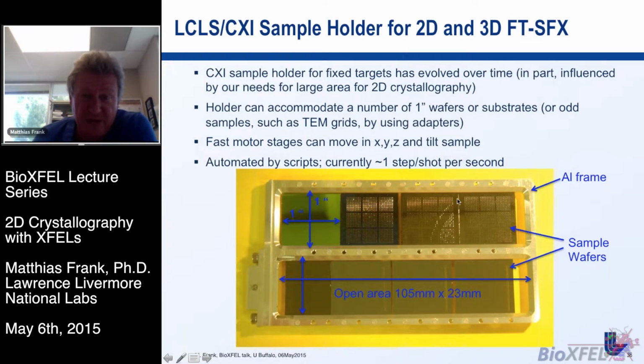So here's an example of one of these sample holders that we used at LCLS. It's an aluminum frame that is made to hold wafers. In this case, these wafer pieces were silicon, 1 inch by 1 inch mostly. You see the bright spots, which are little individual membranes. So there's a silicon wafer that has a silicon nitride layer on it, and it's etched out from the back, resulting in membranes that are supported by the silicon.